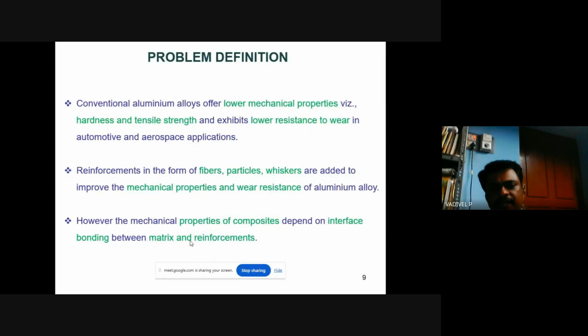The problem we have identified, the challenge we had, is that conventional aluminum alloys offer low mechanical properties. Using the earlier metals like aluminum alloys, the challenge is low mechanical properties like low hardness, low tensile strength, and also the wear rate is high. So we have chosen these three mechanical properties: hardness, tensile strength, and wear. We have chosen these three areas for focusing on conventional aluminum properties. So the reinforcement in the form of fibers, particles, and whiskers is added to improve the mechanical properties and the wear resistance of the aluminum.